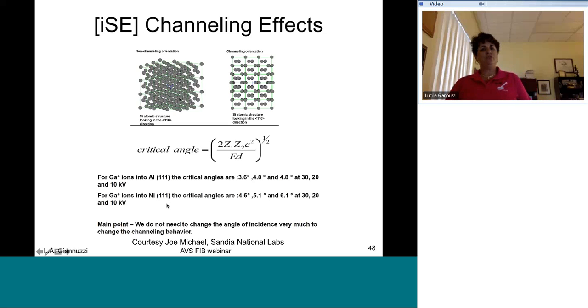So you can see that by just looking down the different atomic structures down different directions, you can see different amounts of open areas. And so what this allows is the ions can travel deep down these channeling directions before they even start to interact with anything or hit anything. What that means is that, for example, along a particular channeling direction, the sputter yield is going to be less because the interactions are going to happen a lot deeper. In addition, your ion-induced secondary electron contrast is going to be darker here compared to, for example, here, where the gallium is going to run into something at the surface a lot quicker than it will here.